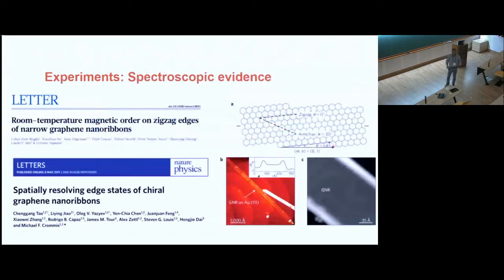Now, the experimental situation is very, very different. You see, at the end of the day, to look at the edge states, we need to have two requirements. You need to have a pristine edge, either zigzag or armchair, so that the electrons don't scatter to another valley. And the second thing is that you need to make sure that the bulk doesn't contribute to the transport. You have to shunt the bulk out.